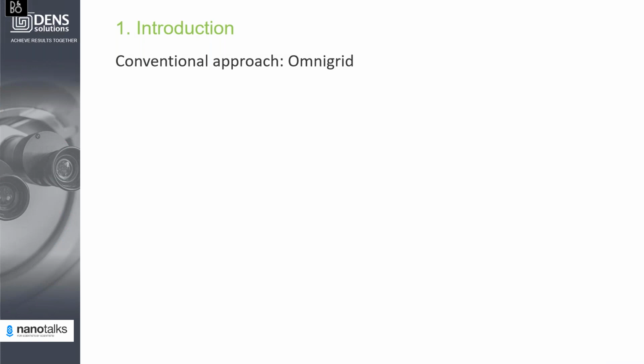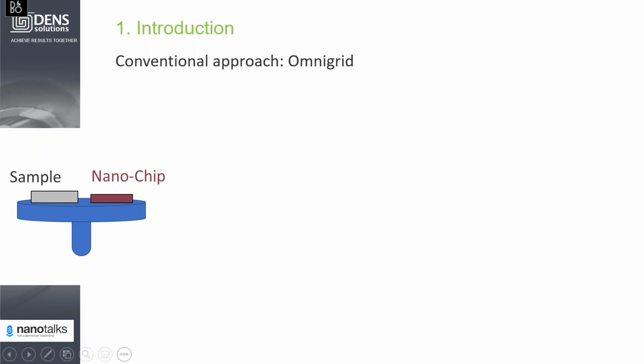So in a conventional approach, if you want to prepare a lamella on the nanochip, you use an OmniGrid. So I'm going to explain briefly the process. You take an SEM stub, and you fix the sample and a nanochip to the SEM stub using carbon tape, and the sample and nanochip are positioned parallel. You prepare a lamella, then you do a lift out. The lift out is done perpendicular to the surface.